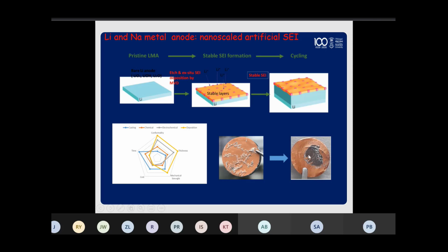And here you can clearly see some results. Again, what we have done here, we have deposited a 15 nanometers alumina layer on top of a copper. And we proceeded in the plating of lithium or sodium, in this case it is sodium, and stripping of the sodium in and out of the copper foil. And you can see this is without the alumina layer. You can see clearly the dendritic formation, while this is with the alumina layer. And I think it's very clear that the morphology and the homogeneity of the sodium that has been deposited is completely different. So the effectiveness of such an approach is actually visually evident.